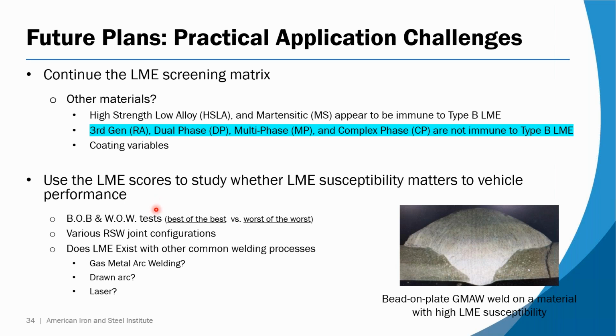And so we have some amount of testing the best of the best and the worst of the worst, the Bob and the wow, as we call it, and putting it in harm's way as far as, what if you have a big fit-up gap? What if you make an edge weld? What if you have these other disturbances? Does that cause LME suddenly to come back even in a good material?